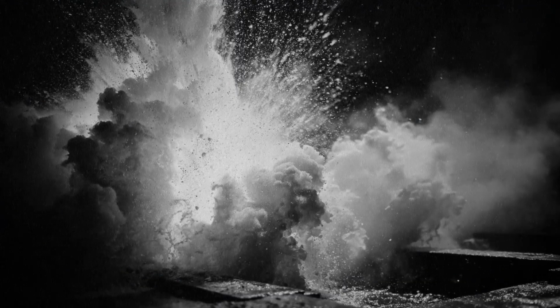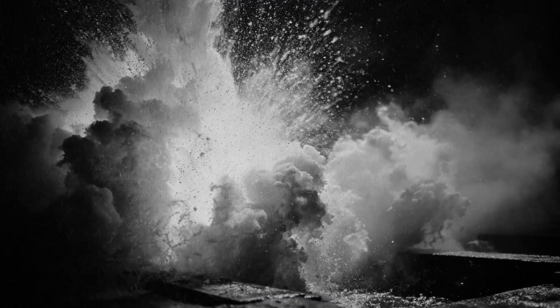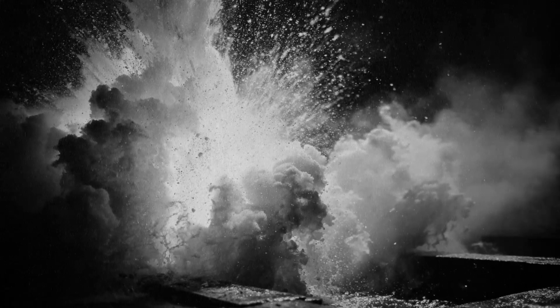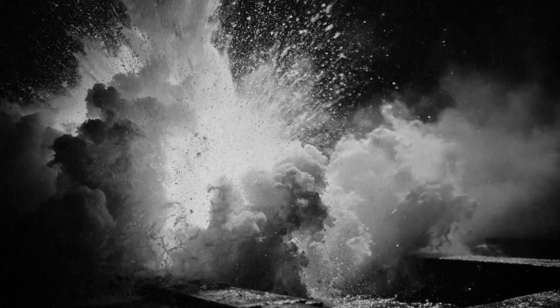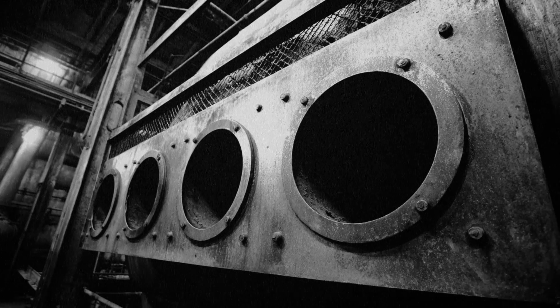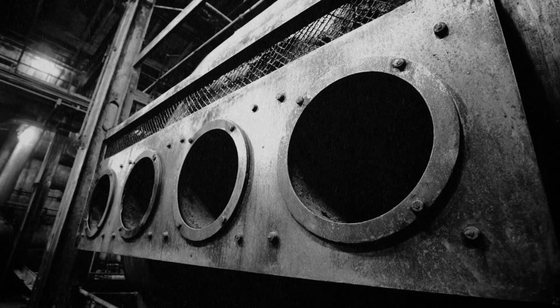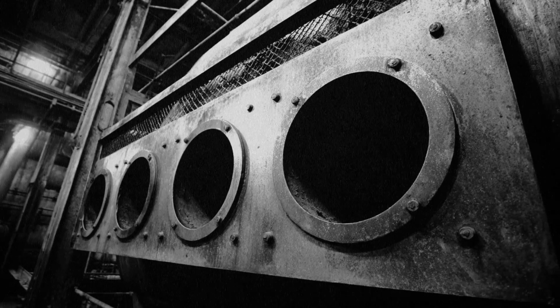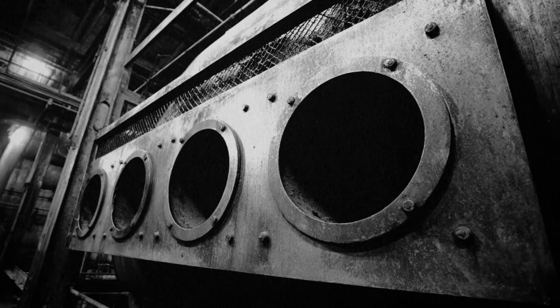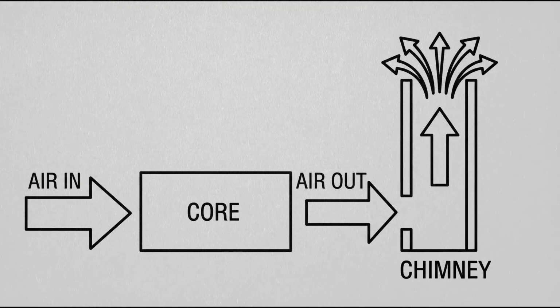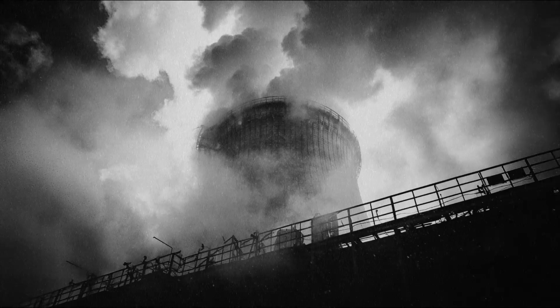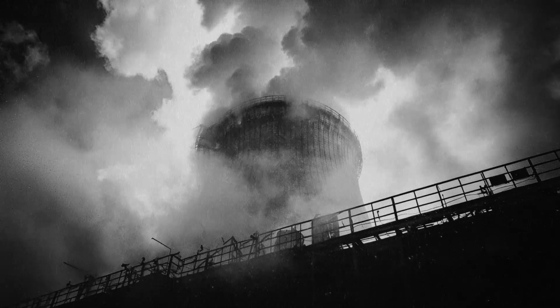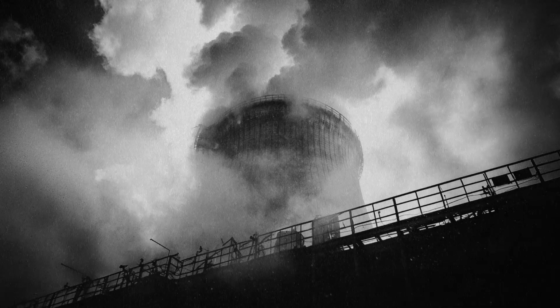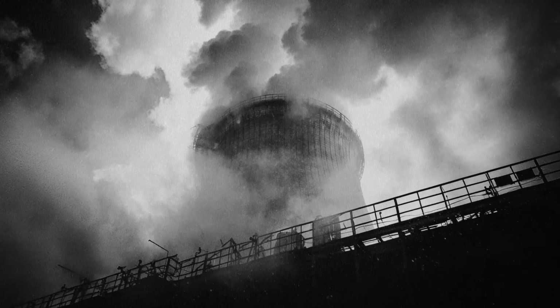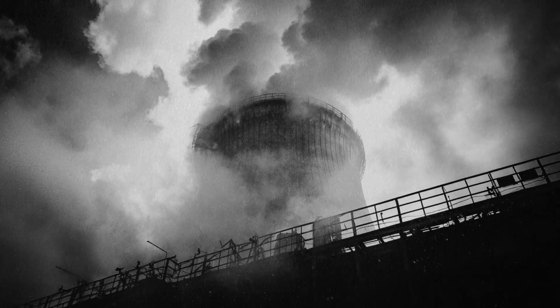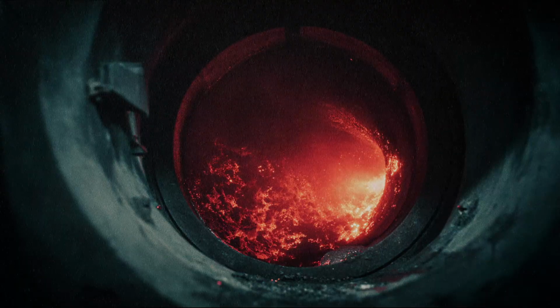But water and uranium at 1300 degrees produce hydrogen gas. And hydrogen, in the presence of oxygen and heat, explodes. To use water, they first had to remove the oxygen entirely. At 10 minutes past 10 on the morning of October 11th, the shutdown fans were sealed. Airflow dropped to 0 kilograms per second. And then they opened the water. 1,000 gallons per minute, poured onto a reactor core at 1300 degrees with no certainty that it wouldn't detonate. It didn't. The fire began to die.